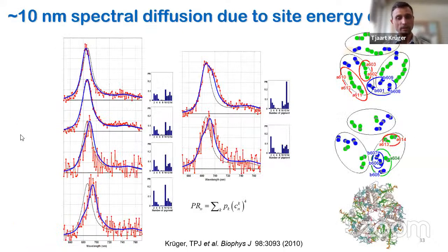Okay, so this is what we did. We did some modeling, and if you take the crystal structure here, we've numbered all the pigments, and we can get the participation ratio of the excitation in the lowest exciton state. So we can relate the spectral shape with the participation ratio of different pigments contributing to the emission. And in most cases, when you have redshifted emission, there's localization of the energy on one or more of the pigments, as opposed to the equilibrium position at 680 nanometers, where you have a much more delocalized state. Okay, so static disorder can explain spectral diffusion within about 10 nanometers.